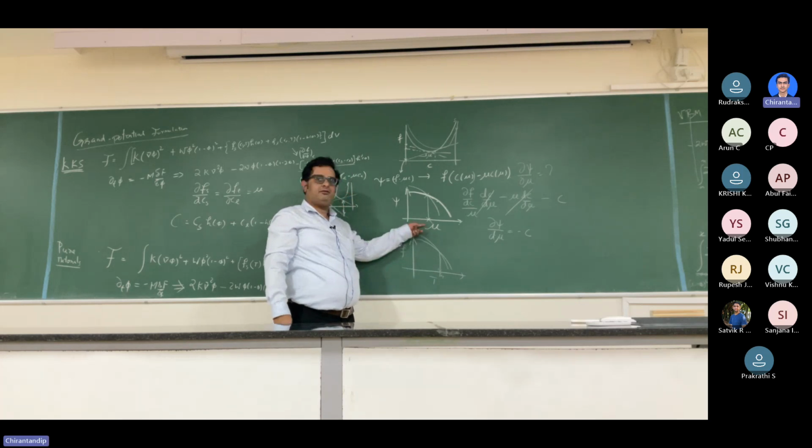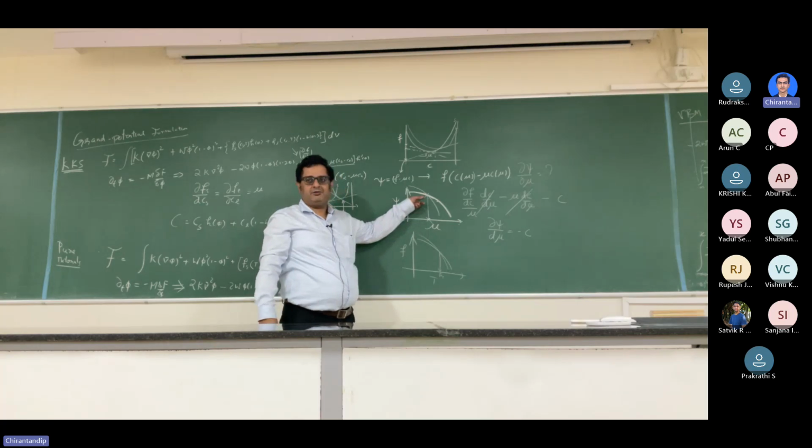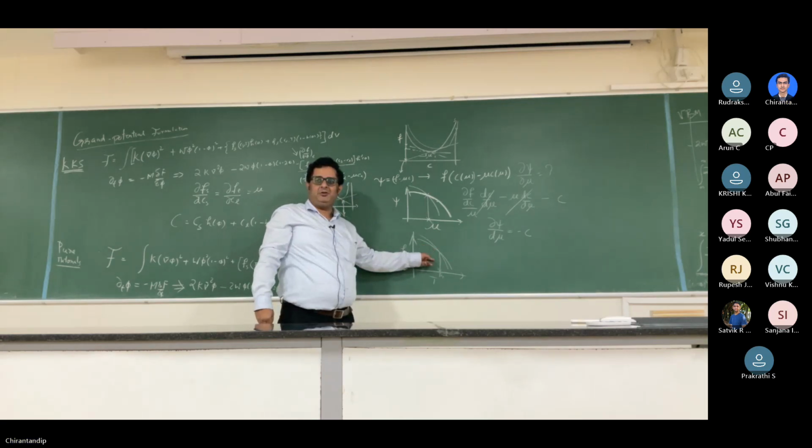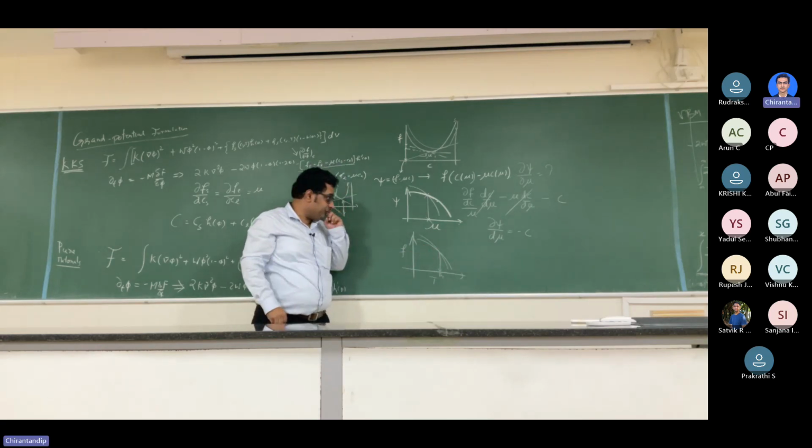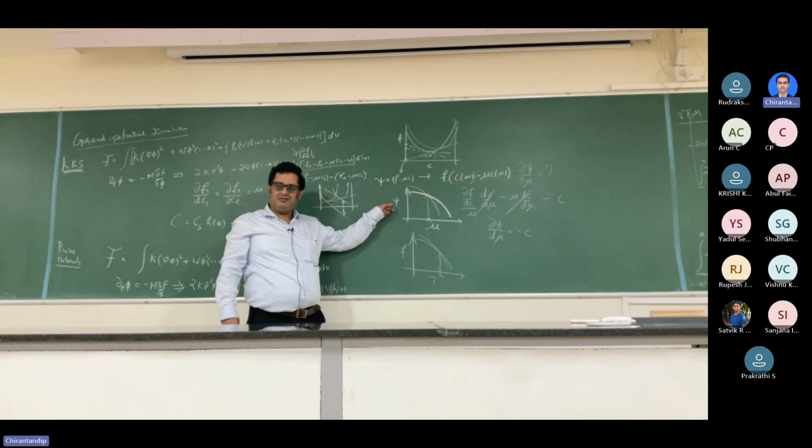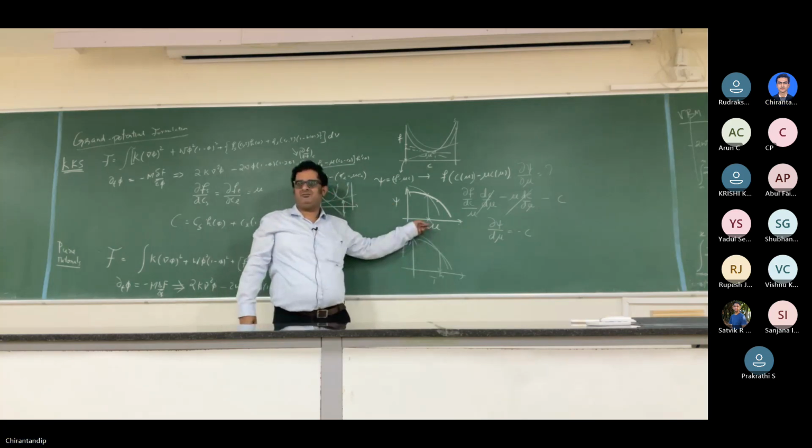Here, at a unique effective chemical potential, your psi are equal. And that's the point of equilibrium, right? The same as this is the point of equilibrium. Okay? So it's an analogous transformation where F changed to psi, T changed to mu.